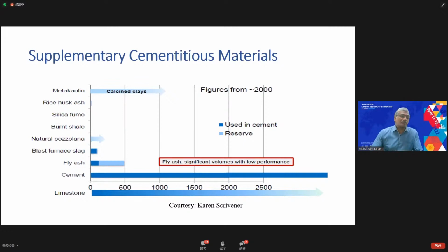Other industrial byproducts like fly ash or slag are often either very limited in quantity, or in the case of fly ash, may be present in large quantities but unusable because of the high degree of variability and poor quality associated with much of it.